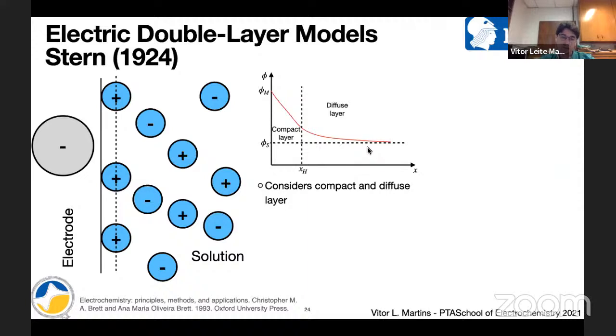That is the ions that will be there compensating charge, but we will have the thermal motion as proposed by Gouy-Chapman. And the profile of the decay of the drop of the potential as a function of distance from the electrode, you have two regions too, right? So you have a linear decrease here that is exactly as in the Helmholtz layer, and then you have this decay as proposed by Gouy-Chapman. So we have here the distance of this rigid layer.